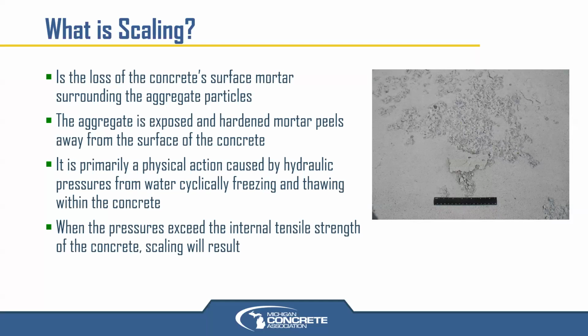Water gets back into that sponge in the winter, and then it freezes, and water expands 9% in volume when it goes from liquid to solid, when it turns to ice. That's why it floats in your highball glass. That's why it floats on top of your ice fishing lake. It's the same weight, but is more volume, so it's less dense. So that 9% expansion in that weak surface paste pops it off and scales that surface off, 3 millimeters, an eighth of an inch, plus or minus a little bit. Depends on a lot of different factors how deep that'll go.